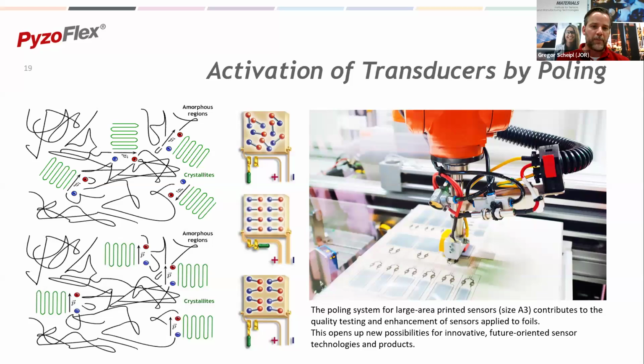On the top, you have this semi-crystalline material with amorphous regions, where the dipoles are randomly distributed, and by applying this electric field, you give them a preferred orientation, which then activates the sensor. And we also at JOANNEUM have an automated poling machine, which is capable of industrial standardized poling up to a size of A3, and this acts as a quality control as well. So we can track or monitor each sensor pixel for the poling current and know how well the sensor is working.